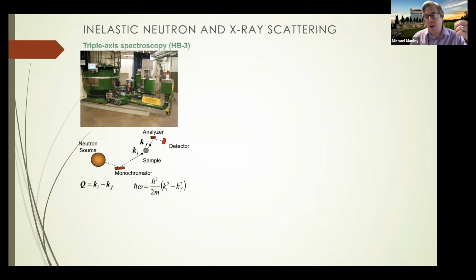And so I will talk about how we will compare two cases, one with the hydrogen replaced with deuterium. So we double the mass of that on the molecule. That'll change the dynamics, and we'll talk about that. First of all, the initial measurement that I'm doing here is a classic triple axis measurement of the phonon dispersion curve. You start with a neutron source. That allows you to select any incident wave vector you want in the range that is possible out of the reactor and the moderator.